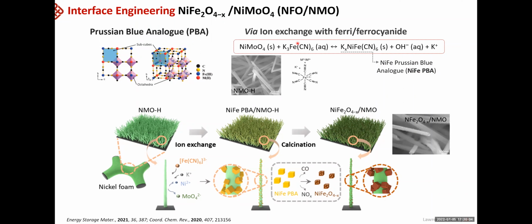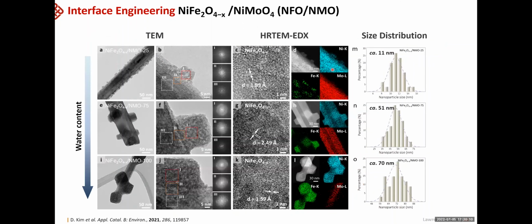During the ionic exchange reaction, we control the content of the water. So we use a water-ethanol mixed solution, and by increasing the water content from 25% to 75% and 100%, we were able to control the size of the crystalline PBA, which actually turned into smaller sizes of the nickel ferrite species. So as you can see in these TEM images, their size is quite different, and we analyzed them as 11, 51 and 70 nanometers. And they all have similar structures from the higher resolution TEM images.